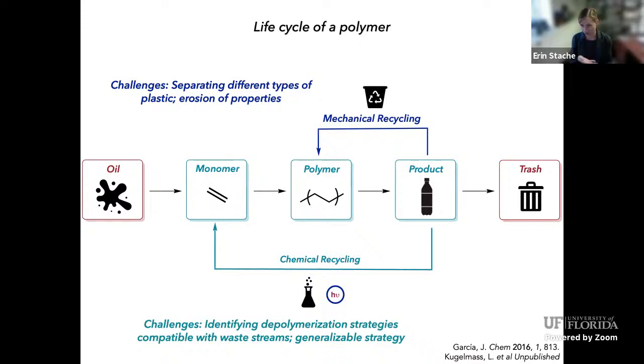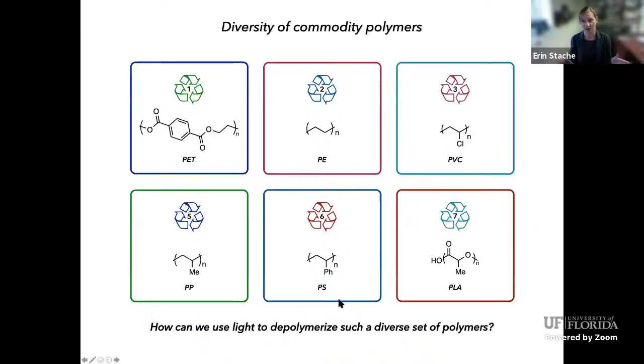So mechanical recycling, that's something that you could use across a number of different polymer types. But for chemical recycling, polymers are very, very different. And if we look at just the diversity of the commodity polymers that we use, looking at our resin identification codes, things from polyesters to polyolefins. Polyvinyl chloride has unique challenges, generates HCl when you try and depolymerize it. Polystyrene, and then the catch-all, which is everything else: polyesters, polyurethanes, polycarbonates. How can we develop a generalizable strategy to try and depolymerize all of these in a chemical recycling strategy? And we ask the question: how can we use light to depolymerize such a diverse set of polymers? So we're going to put a pin in the light for just a second.